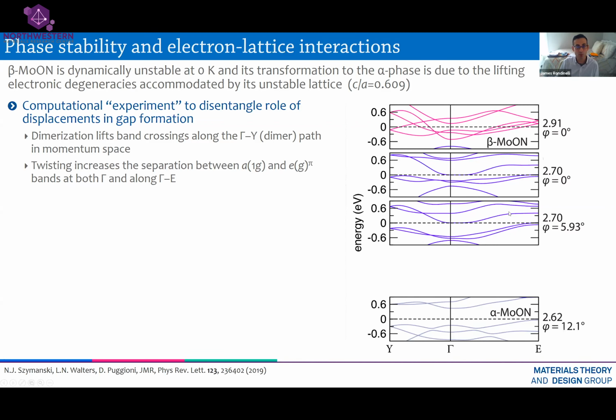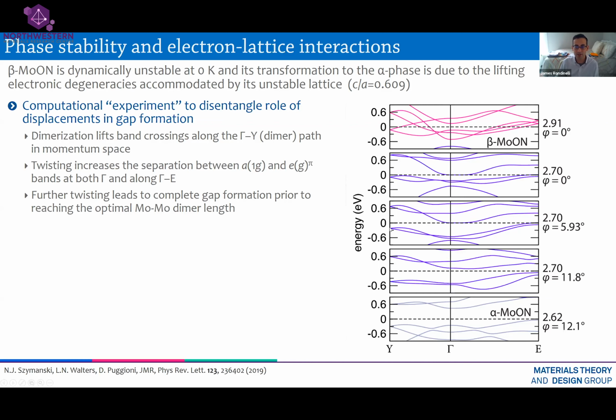But we can identify what is the contribution of each distortion locally to the macroscopic electronic structure, which is shown in this band dispersion on the right. So the details are on the left, but ultimately you see you need both combinations to lead to the gap that you see in the alpha phase. And this is then down here is the alpha phase, or the insulating state of moly oxynitride.